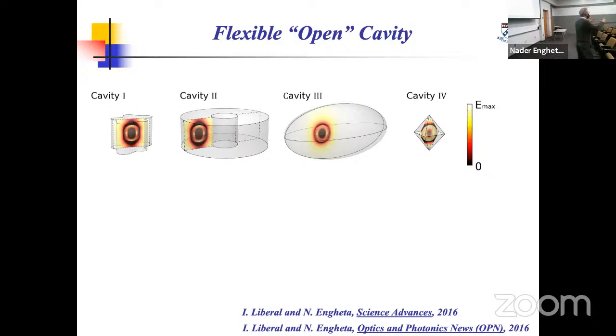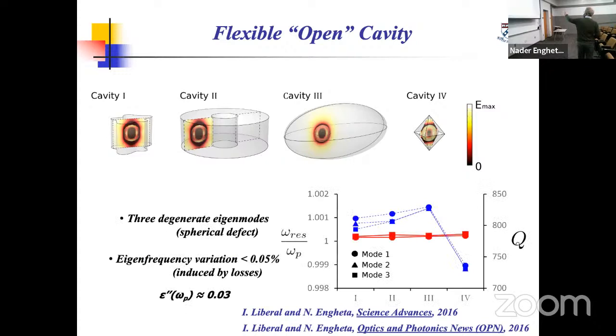So you can have any shape you want, as long as you don't change the dielectric core inside, but just change the external shape. And in this one, you see that the resonant frequency, the red dots that you see on the plot, stay the same, but the quality factor would not stay the same. This is one of those very interesting scenarios where you have a cavity structure whose resonant frequency and quality factor Q are not as conventionally coupled together.